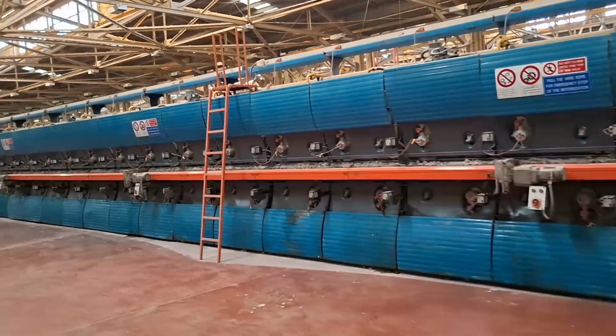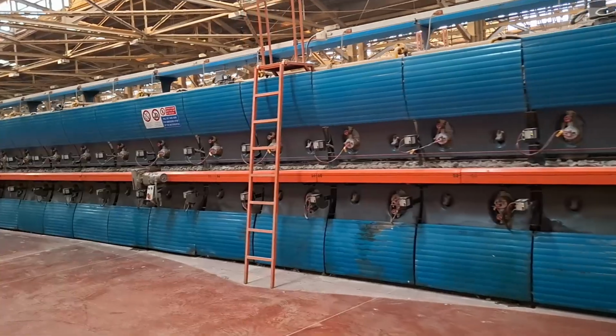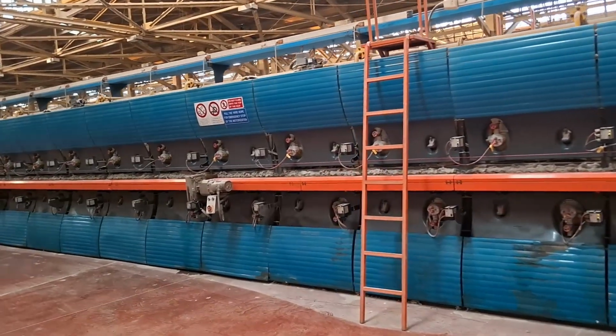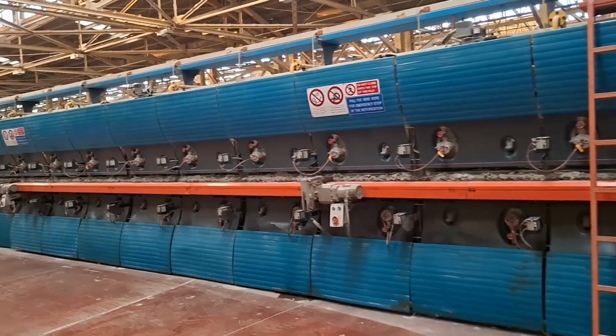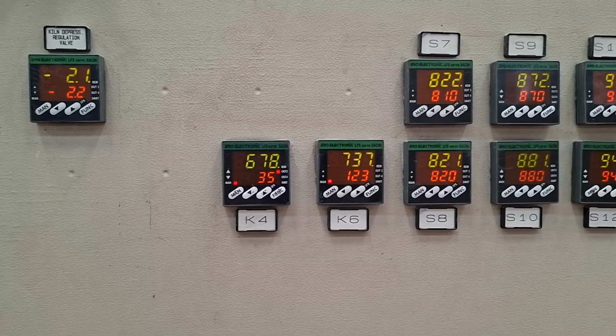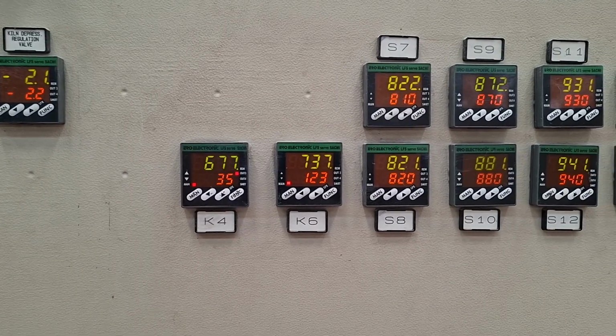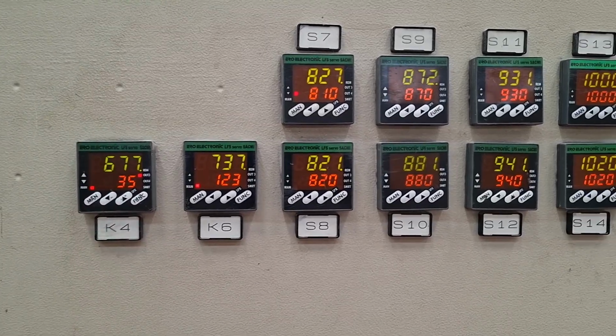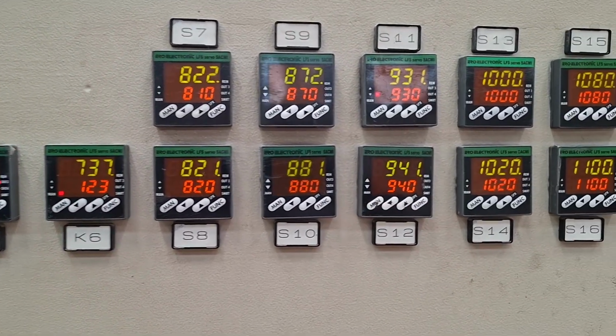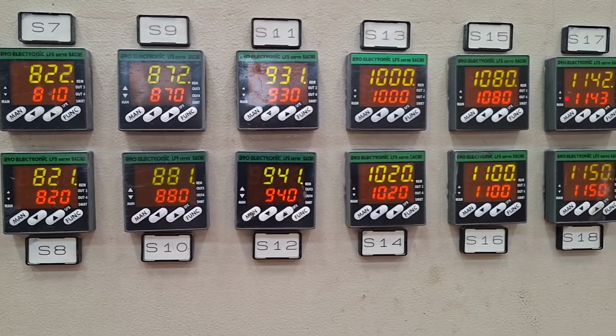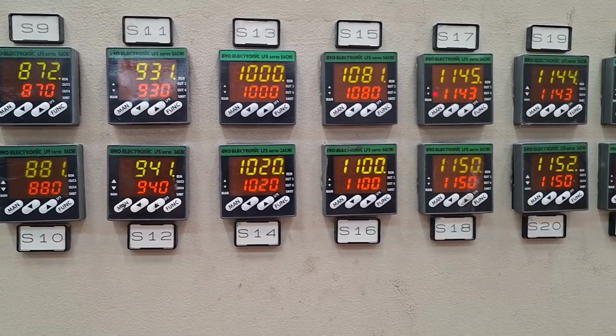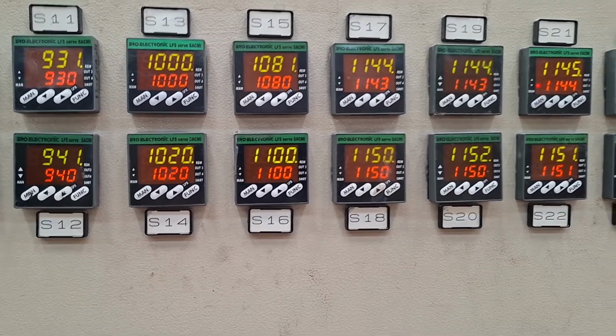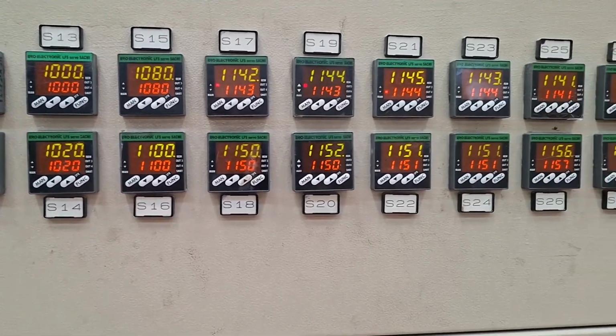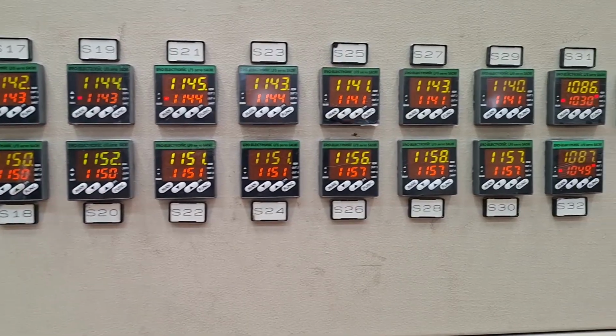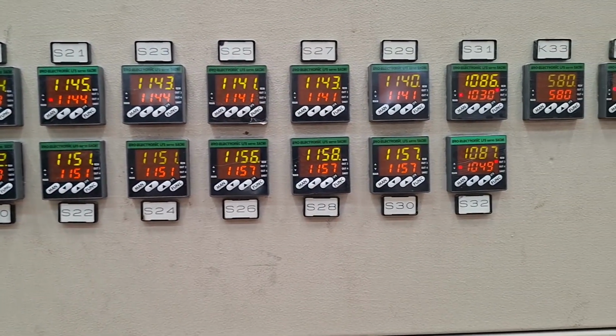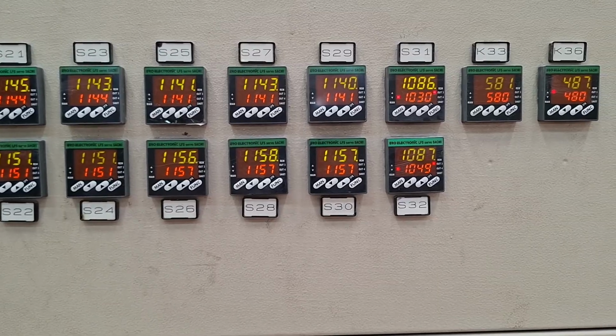Now let's see how everything works together. As soon as the kiln temperature changes, the thermocouple detects it and sends the new reading to the PID controller. The controller compares the actual temperature with the target, calculates the correction, and sends a command to the servo-controlled gas valve. The valve adjusts the gas flow. The burner responds. The kiln temperature moves back toward the set point. Then the thermocouple measures the temperature again. This cycle repeats every second, keeping the kiln stable and the firing process accurate.